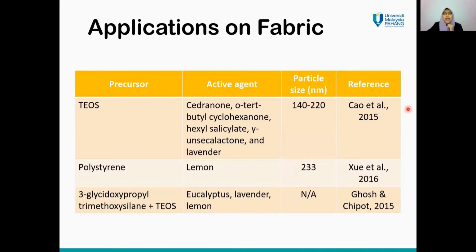Recently, I only found 3 studies on the preparation of nano-sized aroma capsules by sol gel method for fabric finishing, using scientific databases which are Scopus and Science Direct. First is done by Cao et al. in 2015. They synthesized silica nanocapsules in the range of 140 to 220 nanometers by using oil-to-water mini emulsions of different functional monomers as template. The obtained encapsulation efficiency of the aroma is up to 48.1%.